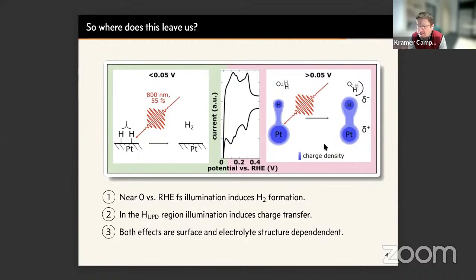We have done similar experiments earlier, not in an electrochemical environment, where you add an infrared pump to this vibrational sum frequency probe. The idea there is that you want to say something about vibrational dynamics with interfacial resolution, and in this case you actually want the medium to absorb as much of the pulse as possible. You do heat the sample, and you can calculate that it's something like a 10 Kelvin increase in temperature over the laser focal spot, but heat conduction is your friend. It diffuses out into solution before the next laser pulse arrives.